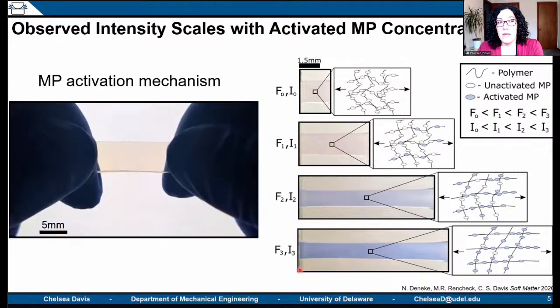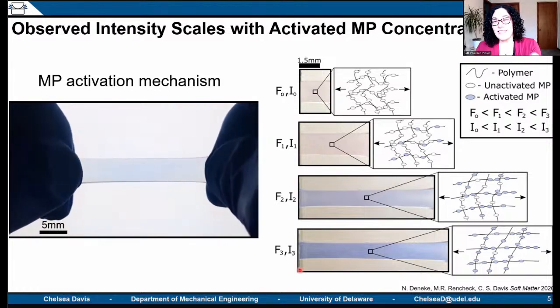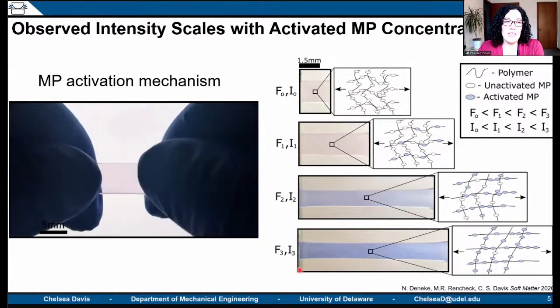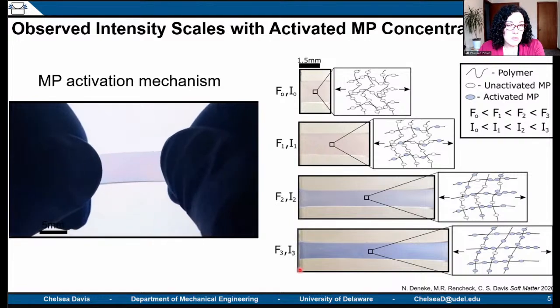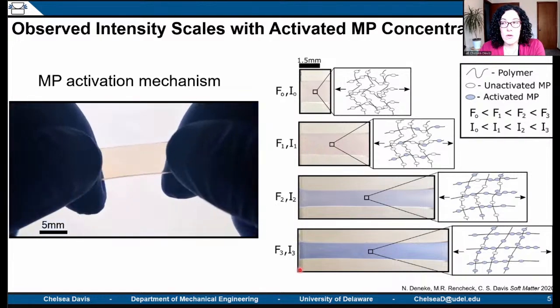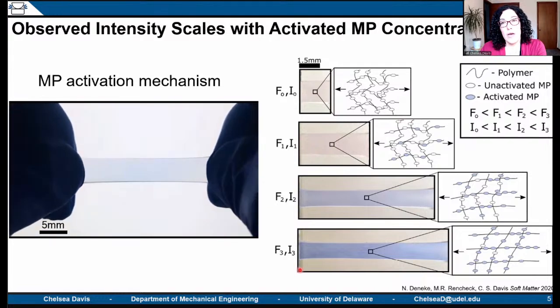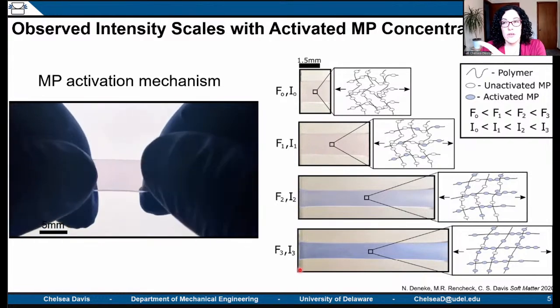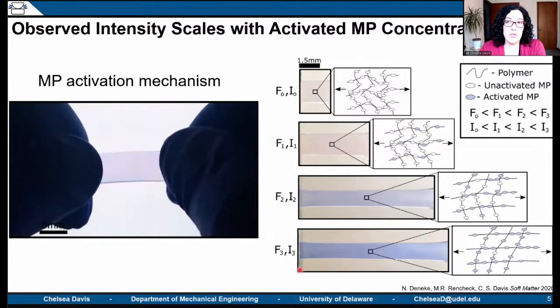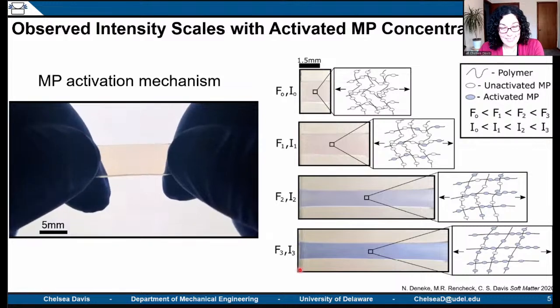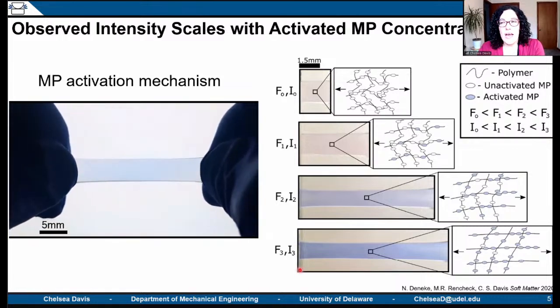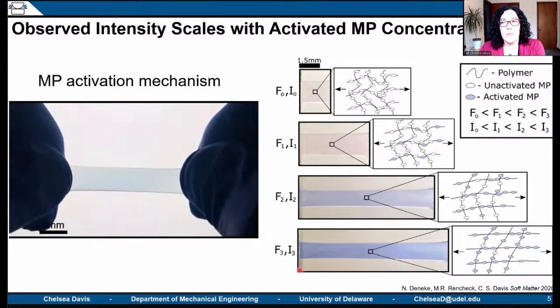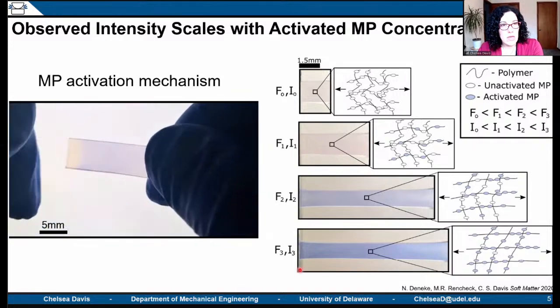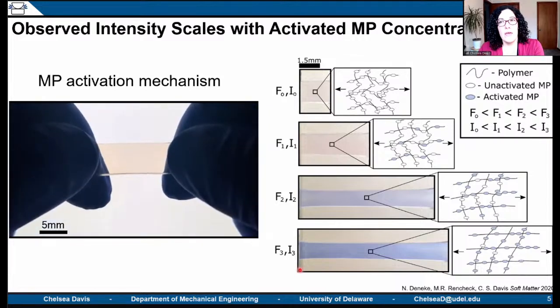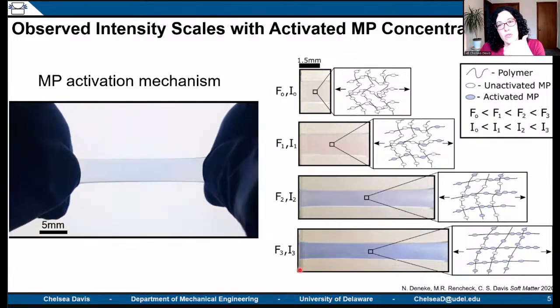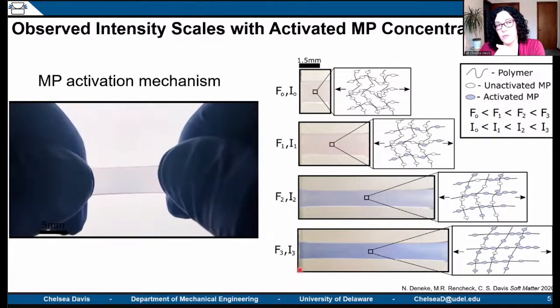I've been told that chemists can design mechanophores with very different activation energies, or forces required to activate them. So if you want to track how much strain or stress or deformation is being applied to your material as a function of the aggressiveness of your ball mill, you would have to be really intentional about mechanophore selection and make sure that you got something that was going to be a fair descriptor over the range of mechanical energy that your system is going to be seeing.